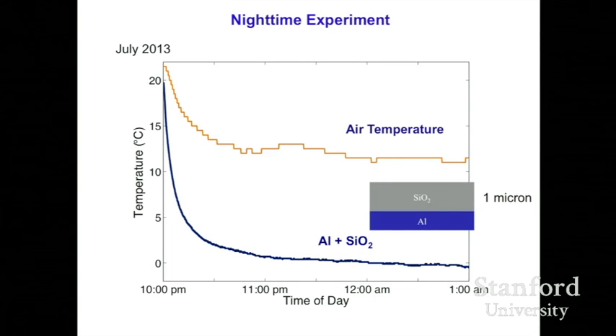Motivated by these theoretical predictions, we then undertook experiments to try to demonstrate it. The initial experiment is a reproduction of the nighttime radiative cooling that people have done, just to show you that cooling can actually be done. So in this experiment, we have an aluminum layer as a reflector with a silicon dioxide layer put on top. It's a very simple structure. And on a relatively warm summer night of about 13 degrees Celsius here, you can get a temperature at freezing. So one really can get to about 13, 15 degrees Celsius below ambient, as people have previously pointed out in the literature.